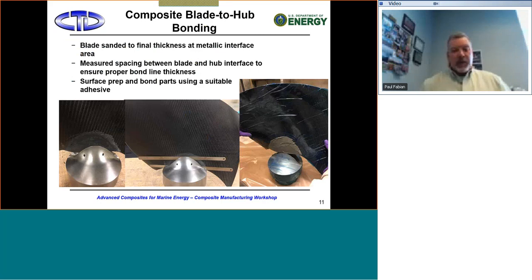And then the next process that we had to go through was actually bonding the composite blade to a metallic hub. This process was fairly simple in the composite industry, but we were using an aerospace grade structural adhesive. And so we did some initial sanding to get the right fit into this hub, and then we had to make sure we were maintaining the correct bond line thickness. So these are just some shims that we know the thickness, and the idea was to keep a 7/1000th of an inch bond line thickness between the metallic and the composite.